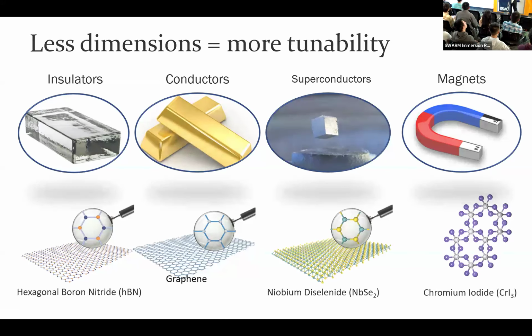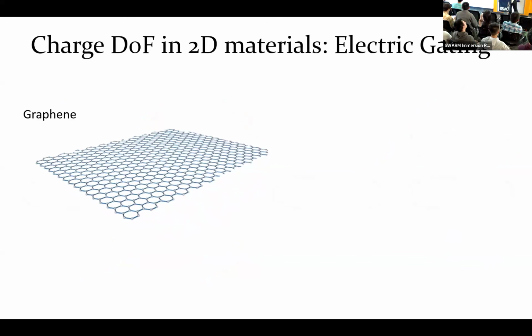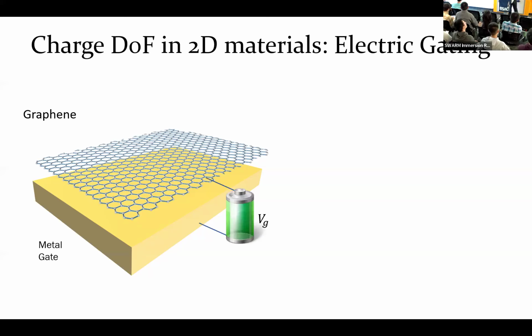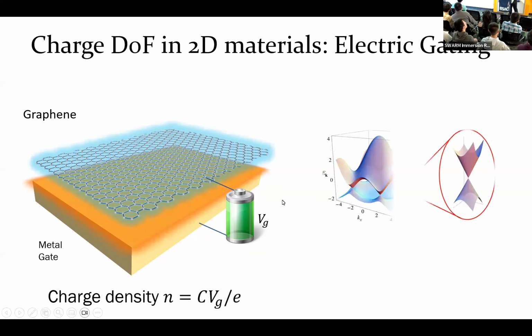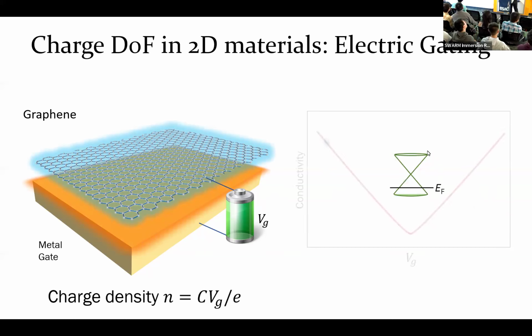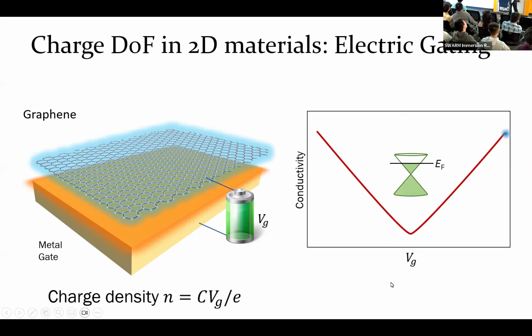But now, what are the benefits? If you just take graphene, for example, one way is that you can simply put a metal gate beneath it, and it is effectively something similar to a MOSFET that you're more familiar with than I am. And you can put a gate voltage between them. You can change the carrier densities or charge density inside the system. And for graphene, you get this kind of Dirac-cone-like dispersion relationship, which means that when you change the gate voltage, you get this V-shaped conductivity curve. And at the charge neutrality, it is a material with relatively low conductivity, and you can apply a gate voltage to tune its conductivity, and so on and so forth.